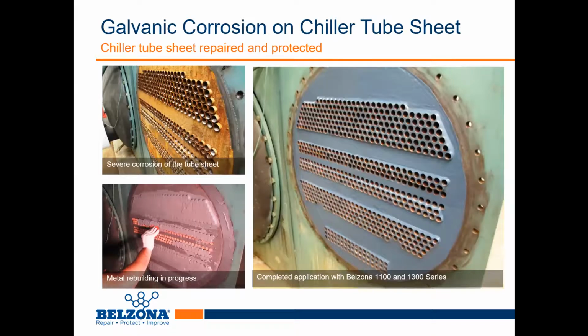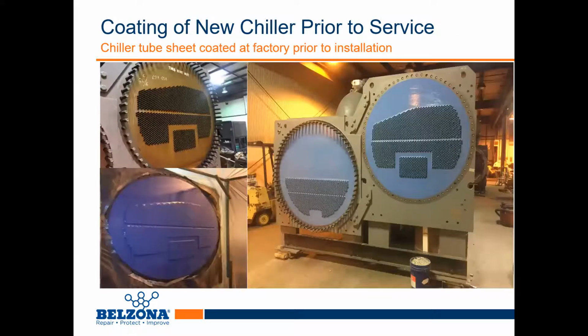So in this next slide, this is a good example. This is a chiller tube sheet that was suffering from corrosion due to galvanic corrosion. The surface was prepared again by grit blasting, washed with Belzona 911 to remove all residual blasting debris. The tubes were plugged, as we mentioned, with corks. And Belzona 1111, a pretty popular product of ours, was applied to the area using this applicator. The 2-coat Belzona system with 1321 was also applied. This offers protection against the effects of erosion and corrosion, and it's going to have outstanding resistance to any kind of chemical attack.